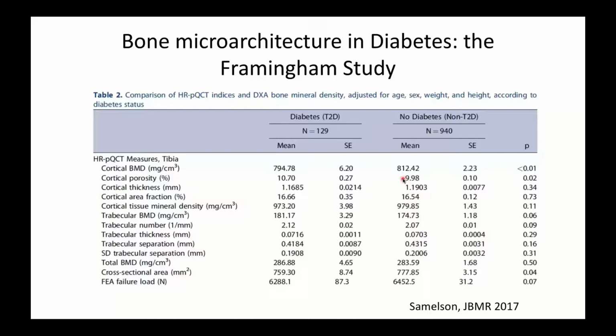And the other parameters, nothing was really different, besides the fact that once again, the trabecular network trends towards a better trabecular volume, thickness, and number rather than a worse one. And the result of that is that the calculated strength of diabetic bones by the failure load, which I remind you is the strongest predictor of incident fractures in non-diabetics, the failure load is somewhat decreased but not significantly so, despite the very large number of subjects.